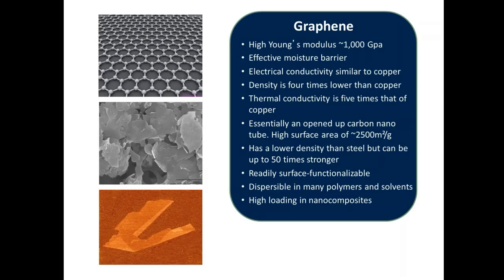Because of its high aspect ratio, meaning very thin but very wide in area, it has functions like moisture barrier, high electrical conductivity, density 4 times lower than copper, meaning lighter than copper but more conducting at times compared to copper, and high thermal conductivity. It has a lot of surface area, so nanomaterials have what we call surface to volume ratio advantages.